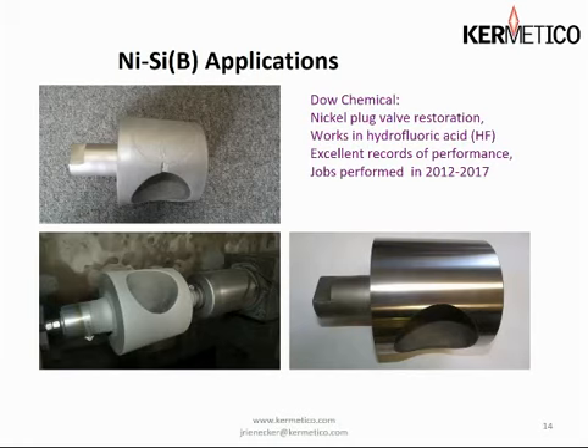This is the nickel silicon boron application I was talking about earlier. We spray a lot of plug valves for Dow Chemical. They have a lot of hydrofluoric acid, and it just eats the nickel alive. Eventually there's some mechanical processes going on, obviously, from the looks of things. But we spray them up, and when they're ground, they look brand spanking new. We do them in batches of a dozen sometimes, and they go into service, and we don't see them for a while.